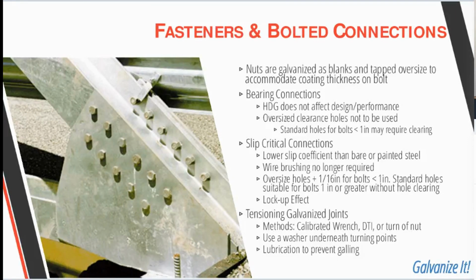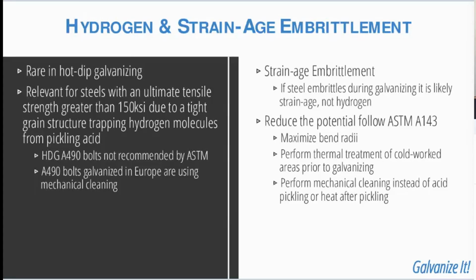When tensioning hot dip galvanized structural connections, a washer should be placed underneath the turning points in order to prevent coating damage during installation as well. The final design consideration for hot dip galvanized bridges that I'd like to review before moving on to hot dip galvanized rebar is avoiding embrittlement and cracking of the steel. This is an infrequent issue, and although infrequent, if a steel member does embrittle during galvanizing, it's very often the result of strain age embrittlement and not hydrogen embrittlement.